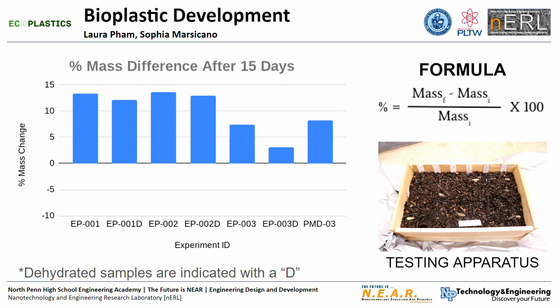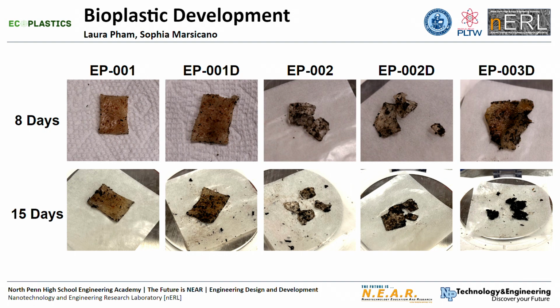Now, our last test was soil degradation. For this test, we used this wooden box here that we made here at North Penn High School. As you can see on the graph, our bioplastics ended up gaining mass instead of losing mass. This was due to water absorption because our plastics were very porous. Despite our plastics gaining mass, there was noticeable degradation in all of our samples, especially EP-002 and EP-003 dehydrated.